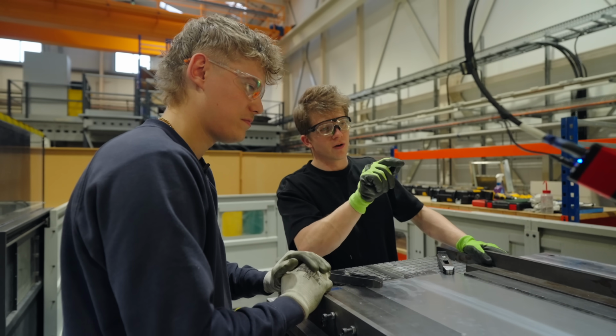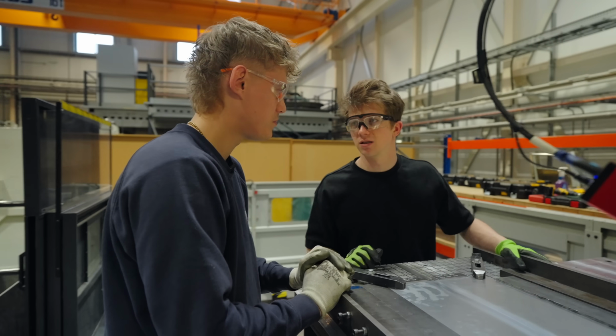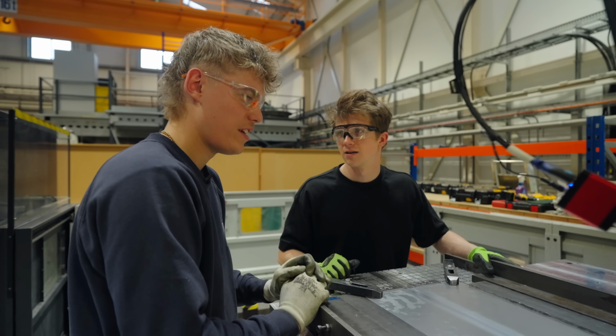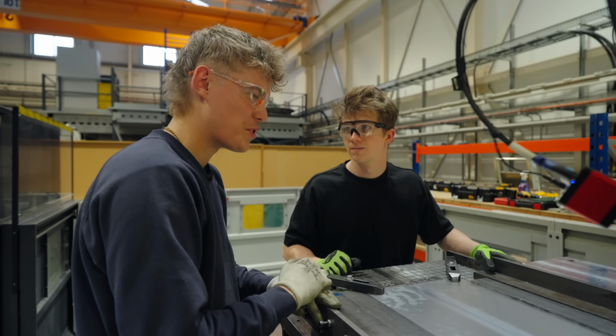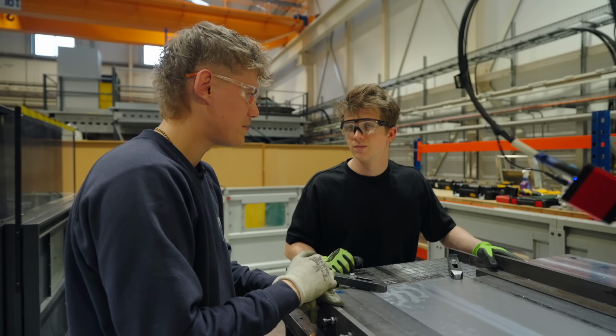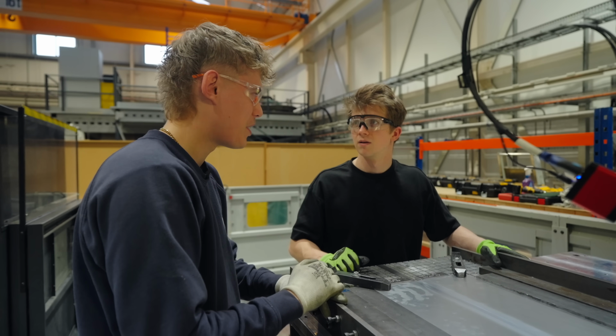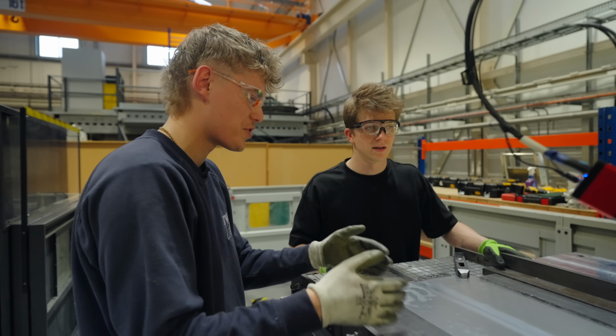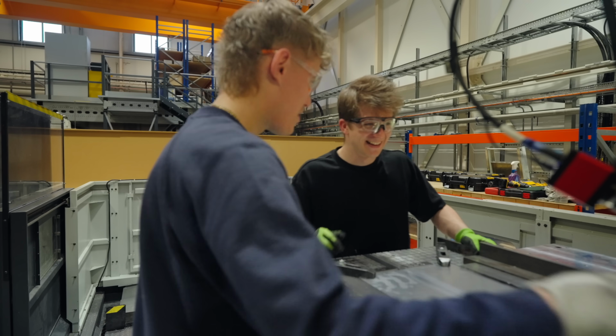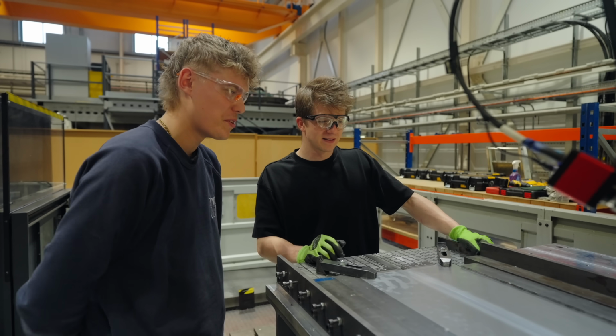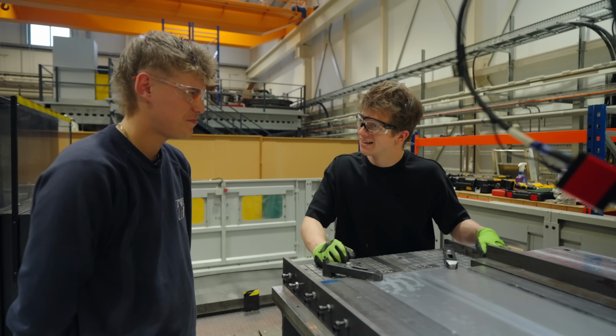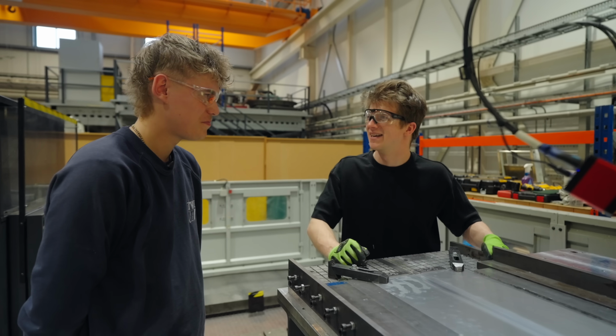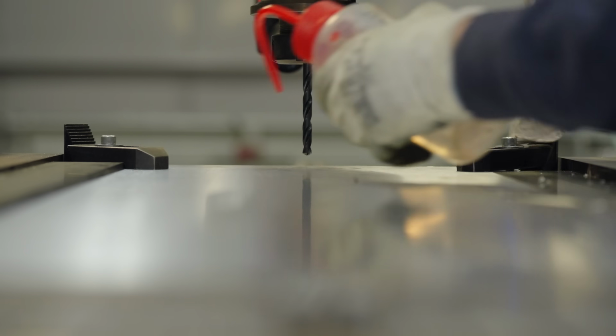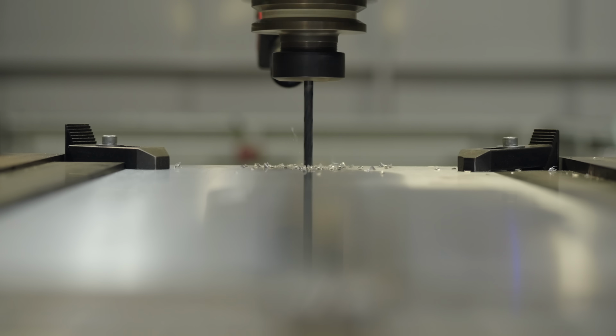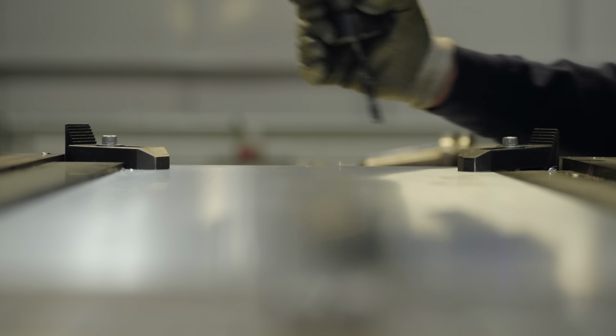What's going to be different running through this 10 mil aluminium compared to the copper? Any different feeds and speeds? Well, we can go a lot faster. I think we weld at 250 over there, and we're welding about 800 over here. Wow. We generate a lot more heat over there, whereas this won't get as hot. Okay. Copper likes to soak in a lot of the heat. We have a small ramp at the start to accelerate, and then we'll be going almost a metre a minute. A metre a minute? You're going to be welding 10 mil aluminium a metre a minute? Yeah. What are you doing now? We're in our pilot hole, 8mm deep for the probe, because otherwise your probe's doing all the work going down the hole.